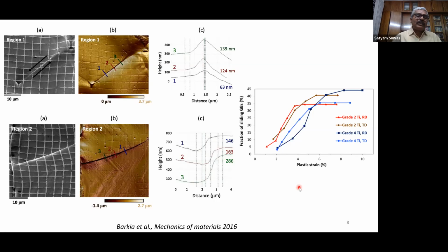And the one particular thing that we have seen is if we take the microstructure of titanium and carry out the deformation, from region to region we see that there is a difference in the sliding of grains. We can see it here. There is a difference in sliding of grains in these materials. So this was considered as a phenomenon that also depends on grain boundary sliding. So this is one reason. So first is strain rate sensitivity. Second is anisotropy, that means the texture. Third is the propensity of grain boundary sliding. And then this again is a function that is sensitive to the direction and the texture of the material, right?